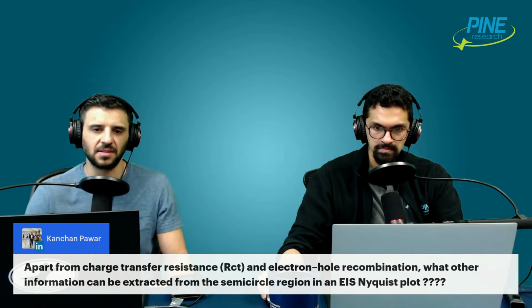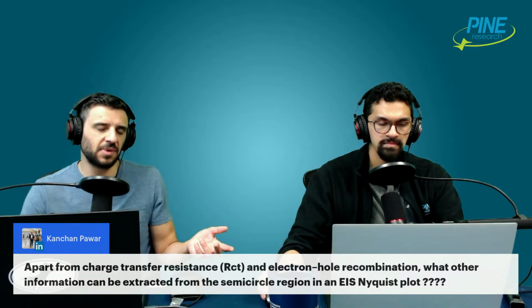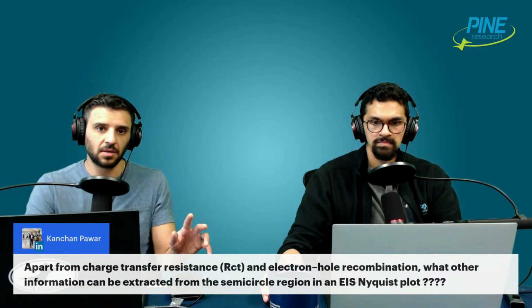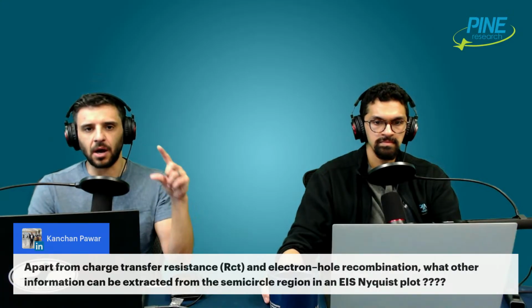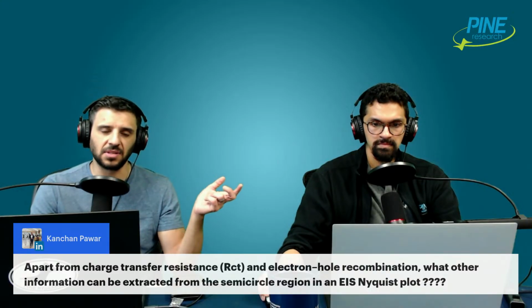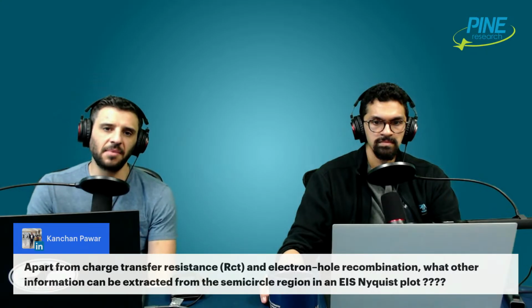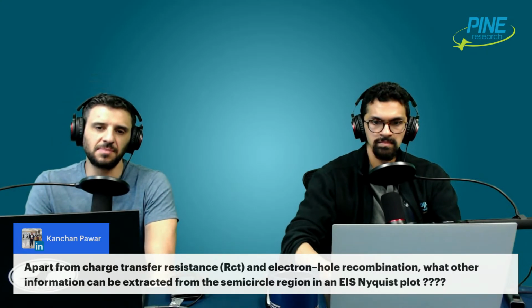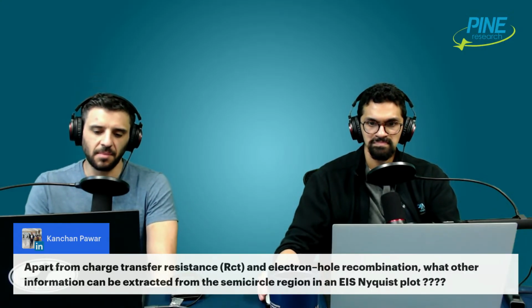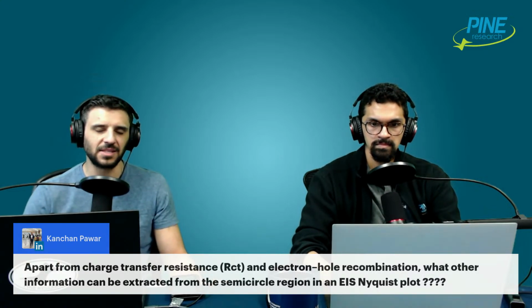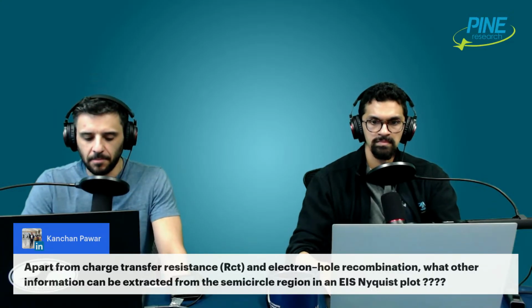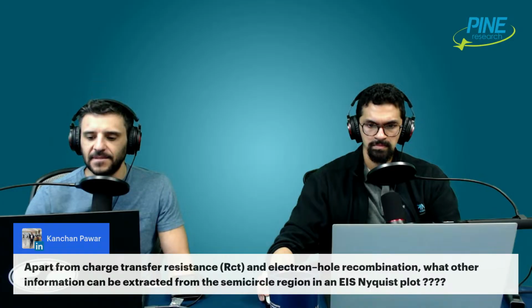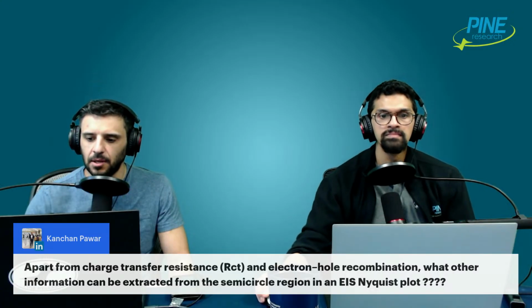There are estimates where people say 5x that is the speed. That's roughly the speed. Generally speaking, if I have an RCT and I have a capacitor, that's the semicircle, but it's an R and a C. I multiply R times C and I get some amount of time, usually maybe microseconds, something in that range. That is what's called a time constant. And that's basically, relatively speaking, the speed associated with that charge transfer process. So that's one of the main quantitative diagnostics that we can get from the semicircle region in a Nyquist plot. I think that's probably the most direct thing I can think of. There might be other tangential things, but that's the most obvious one that comes to mind. And then Nikhil, I guess, will answer the next one.